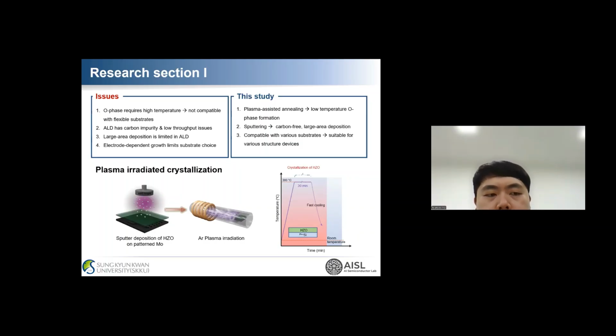In this work, we aim to overcome this limitation by using plasma irradiation to induce the orthorhombic phase at low temperature, combined with sputtering for large area deposition. Specifically, we use argon plasma to control oxygen vacancies and promote the formation of the orthorhombic phase. Also, hydrogen plasma is generally more reactive and enhances reduction, but we intentionally use only argon plasma and achieve better results compared to hydrogen-based plasma.